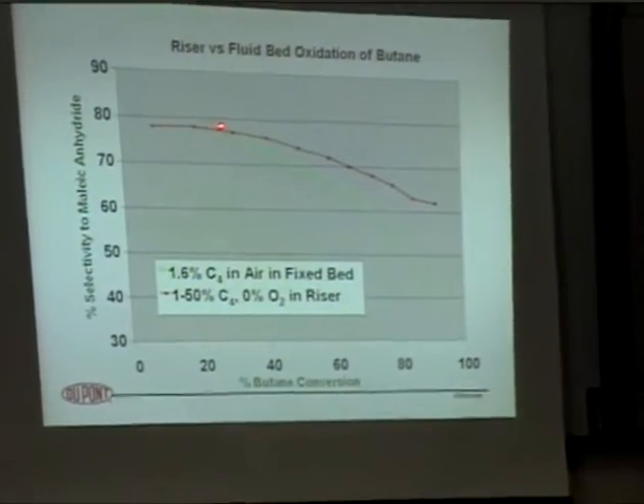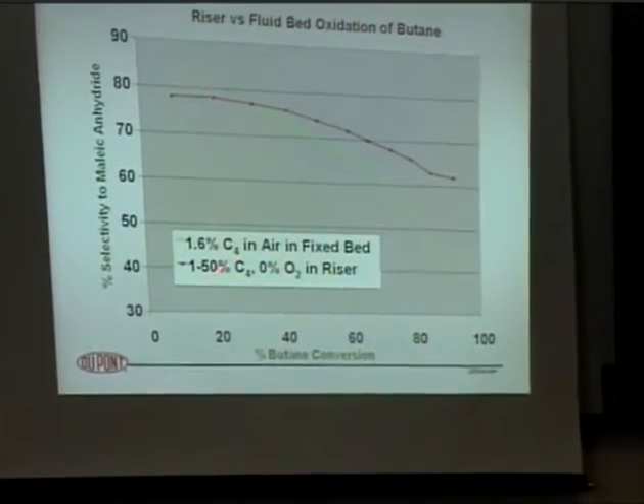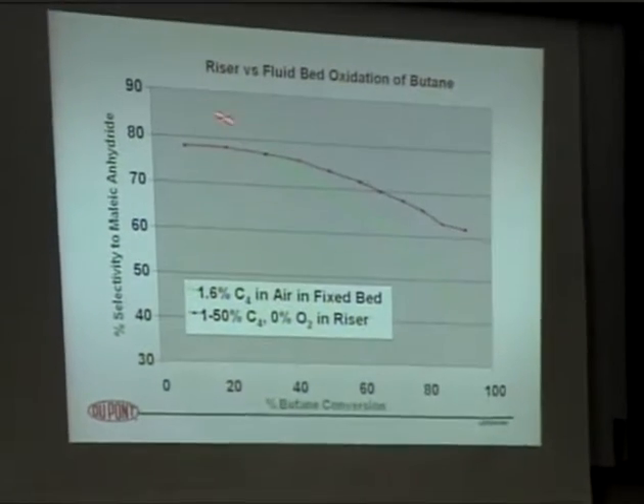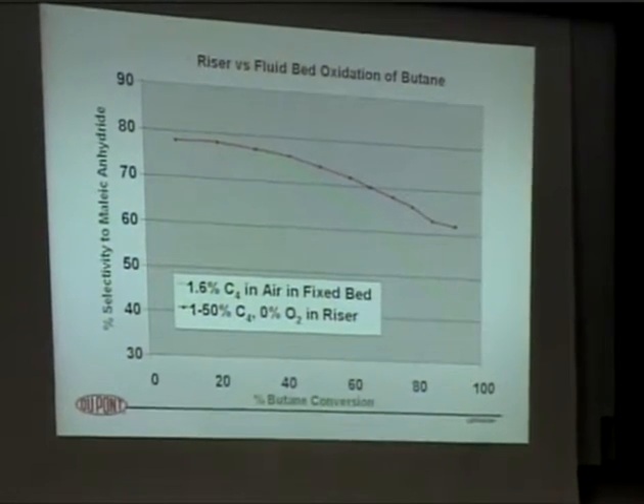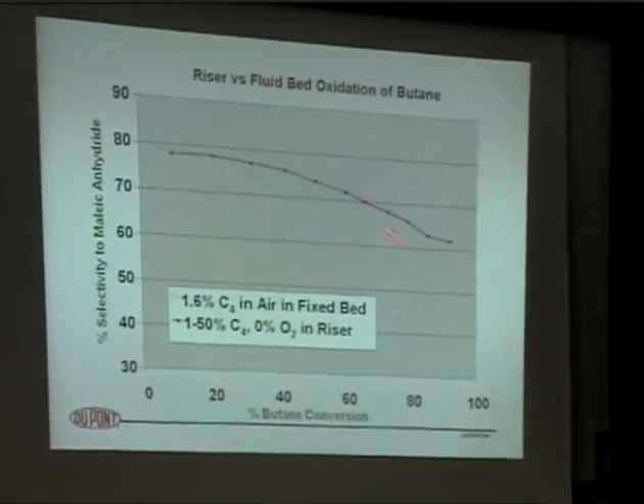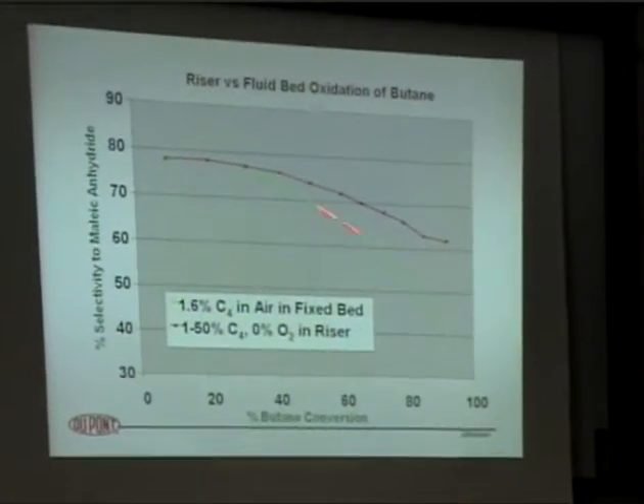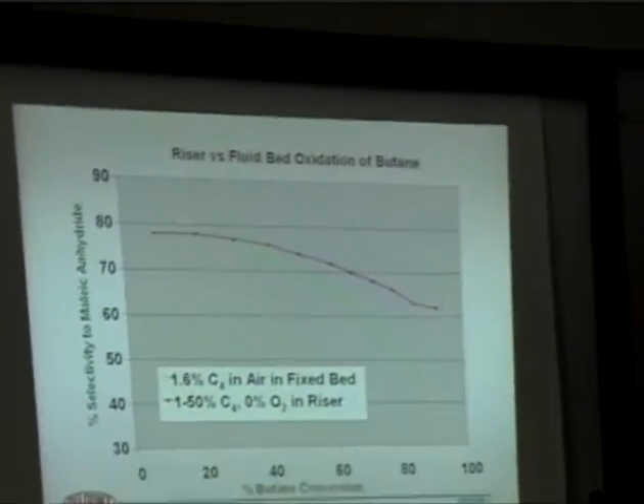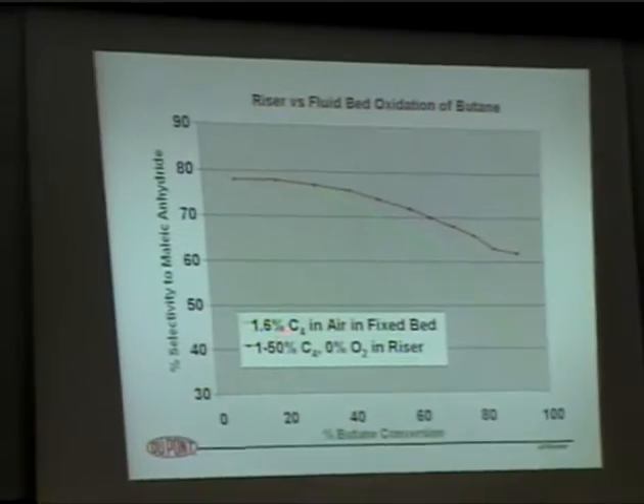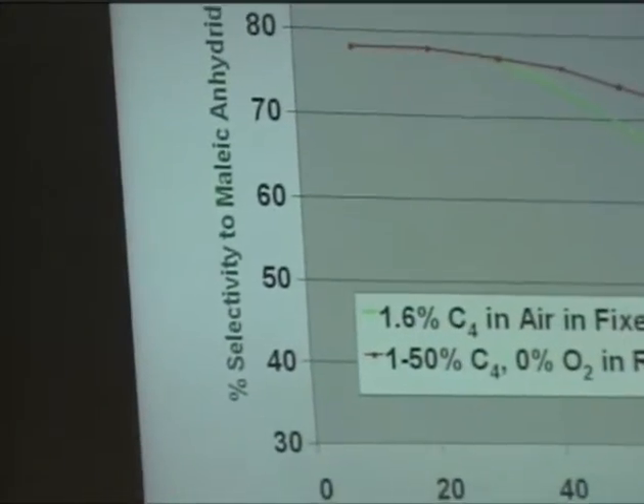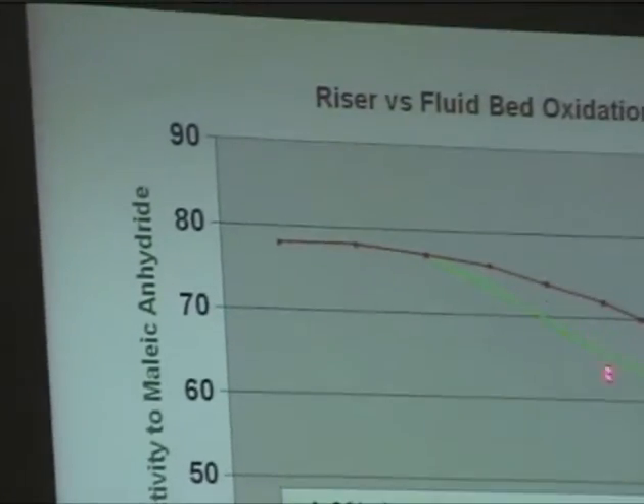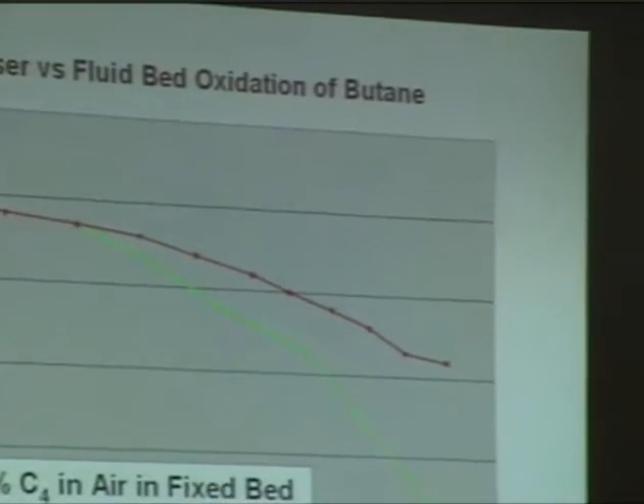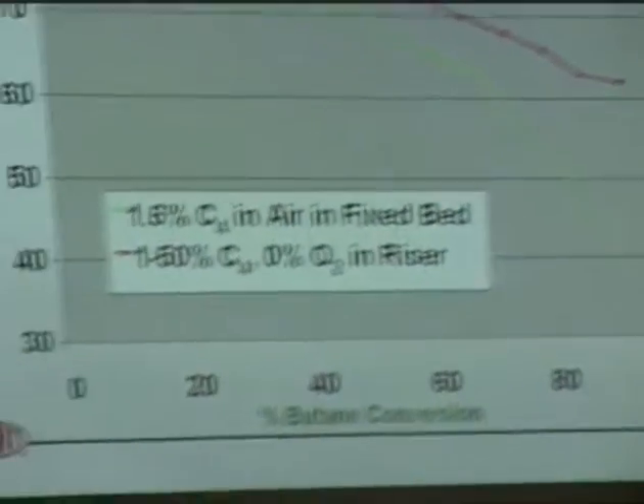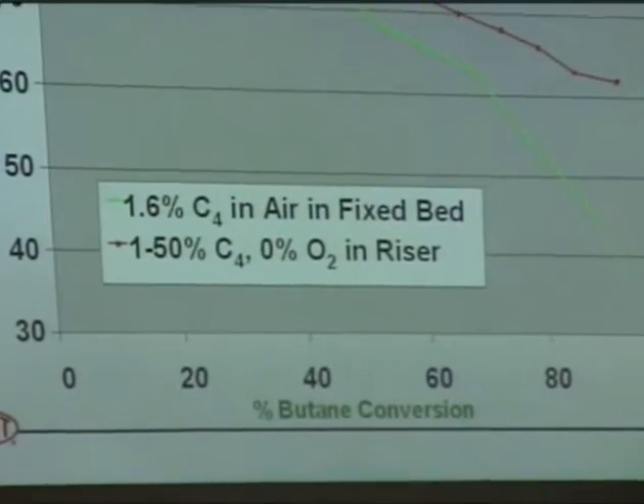This is actually a small little reactor we ran in the laboratory, but if you run with as much as 50% butane, you can maintain selectivities well over 60% versus the more traditional 50 to 60% that you see in fixed bed reactors or even fluid bed reactors with only 1% or 2% butane in the feed. So there is an advantage from a selectivity standpoint and an investment standpoint in running the butane oxidation process that way.